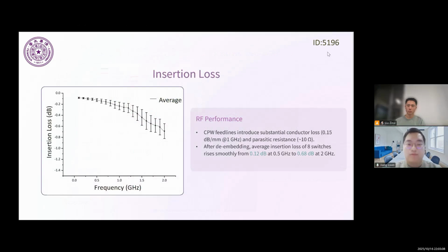Now for the RF performance. After de-embedding, the average insertion loss across 8 switches is 0.12 decibel at 0.5 GHz and 0.68 decibel at 2 GHz. The variation is within 0.2 decibel, which shows good uniformity.